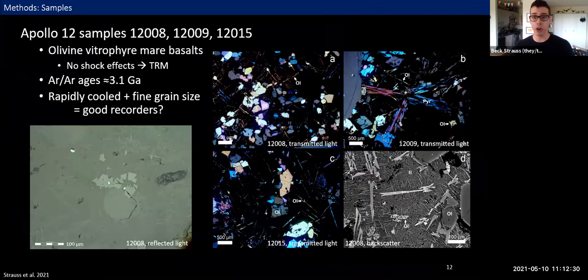All three of these samples are olivine vitrophyre mare basalts, and our microscopy didn't turn up any evidence of shock effects, which we interpret to mean they were likely magnetized through a thermal process, gathering a thermoremanent magnetization, or TRM. We determined new argon-argon ages for two of these samples and the first ever argon-argon age for the third, dating all three of them to right around 3.1 billion years ago, exactly what we had hoped.